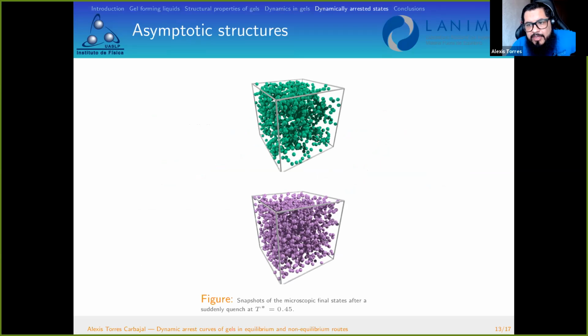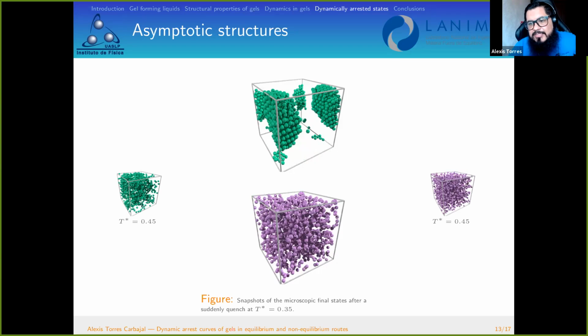We can trace this difference if we look at the microscopic final structures. For instance, if the temperature is near 0.45, that is a temperature above the critical point of the reference systems, both fluids remain in the fluid phase. But if we decrease the temperature, we observe that the Lennard-Jones fluid separates in phases, while the Lennard-Jones with Yukawa tail remains in a fluid state.